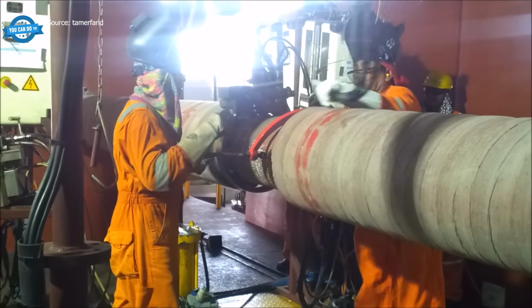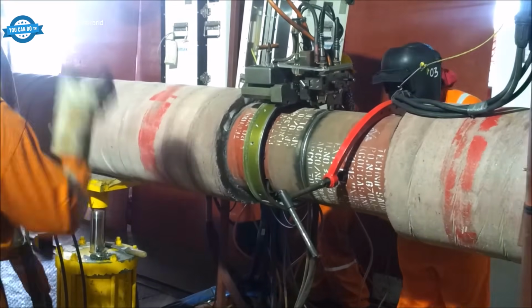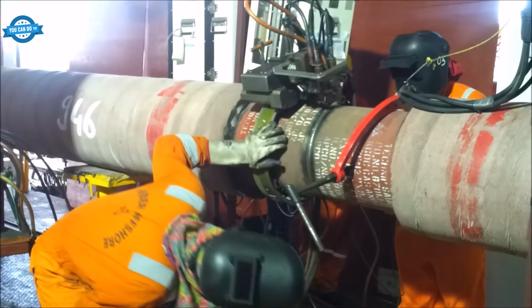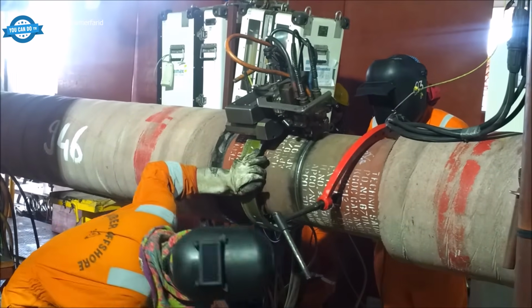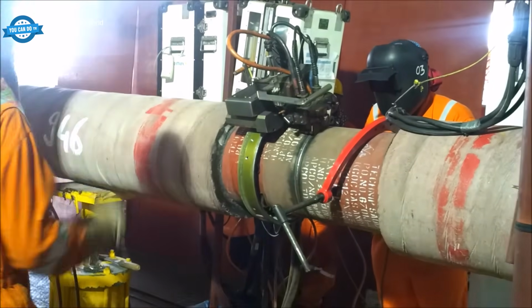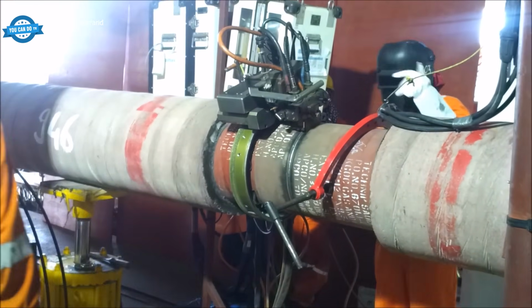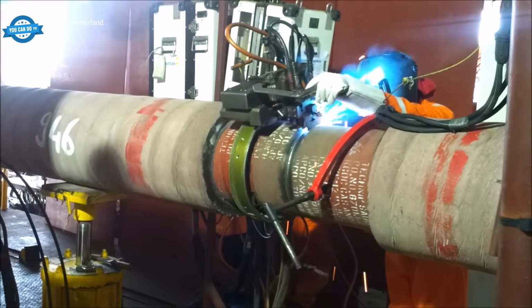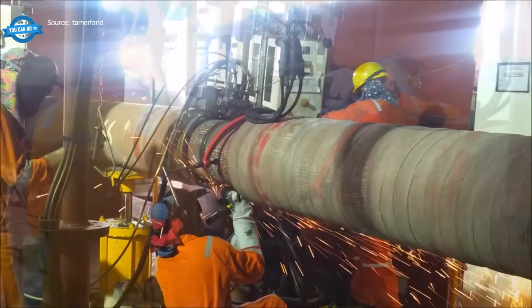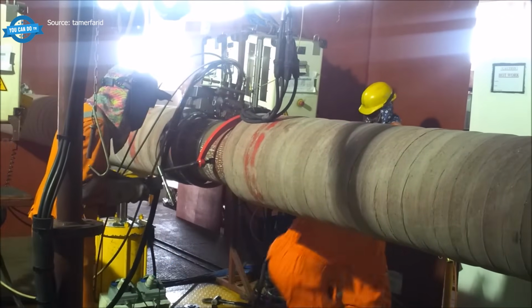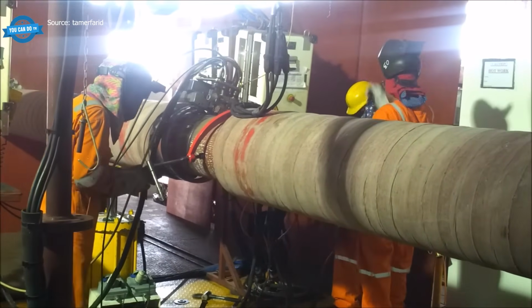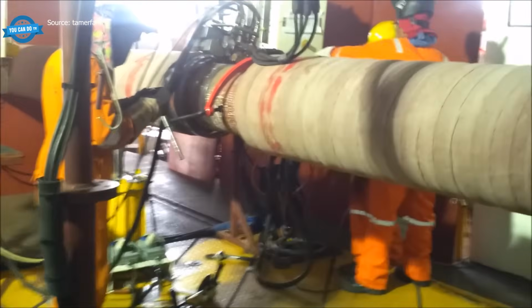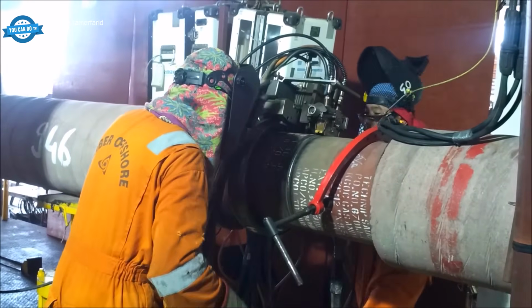Offshore, the field joint coating happens on a moving deck in open weather every few minutes. Inside the firing line of an offshore pipelay vessel, each pipe section is welded to the next while the line steadily advances. The bare welded zone, around 200 to 400 millimeters wide, exits the welding station and immediately enters a coating station built into the deck.